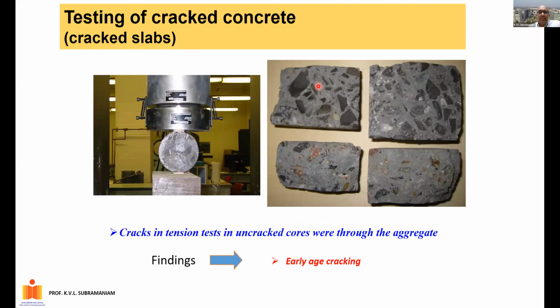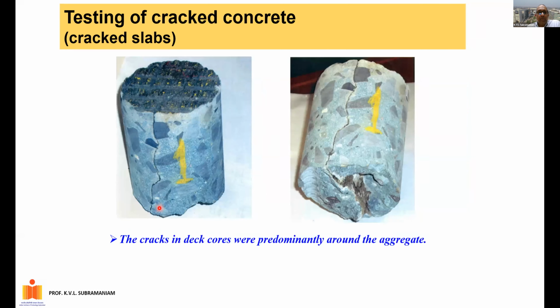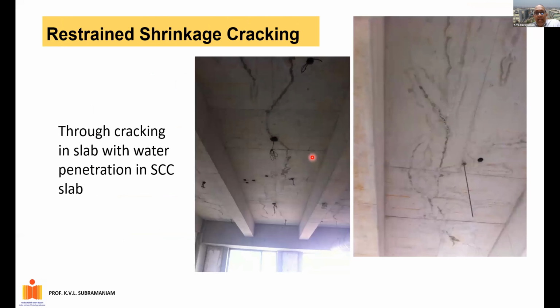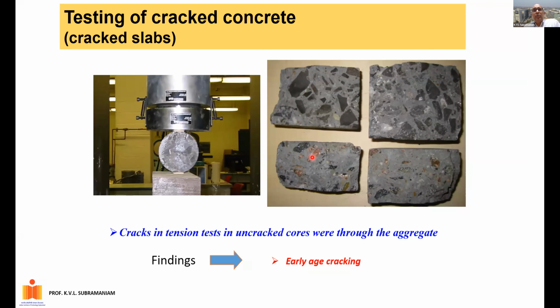That means once the concrete became strong, once it had gained strength, the mortar in the concrete is stronger than the aggregate, because all the aggregate are split in the split tensile test. So this is what led us to believe that this crack was formed at a very early age. And it was established that this crack was formed because of shrinkage. Concrete wanted to shrink, and the shrinkage was prevented, and that's what resulted in this cracking.